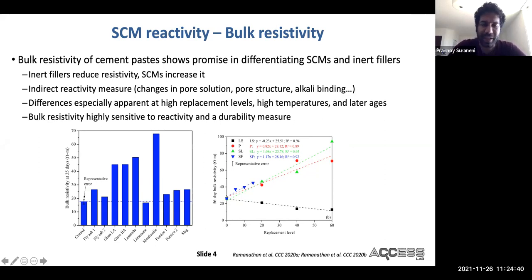The bulk resistivity is actually a somewhat indirect reactivity measure because it is affected by changes in pore solution, pore structure, and alkali binding. Some of these are directly related to reactivity, some not so directly. So it can be a little complicated to interpret, especially if you're trying to use quantitative values, but qualitatively, it's a great screening tool, especially if you use high temperatures, high replacement levels, and later ages. The nice thing is that bulk resistivity is highly sensitive to reactivity, and it can at least be used as a qualitative durability measure.